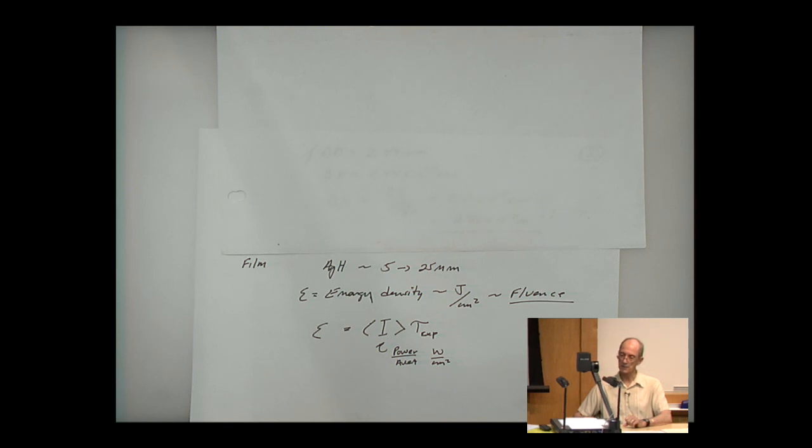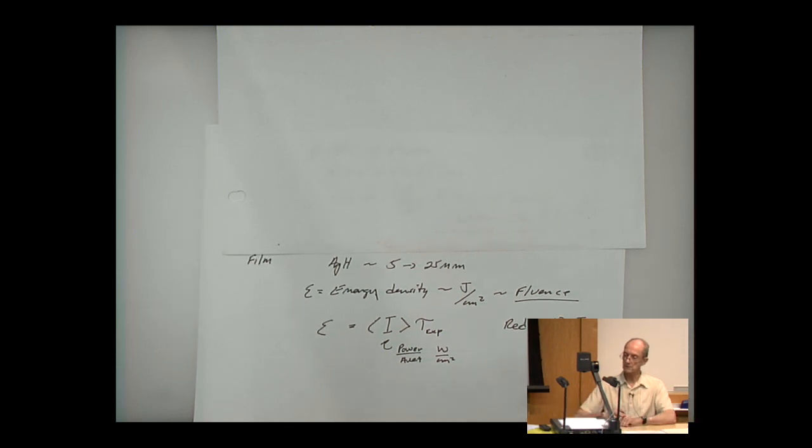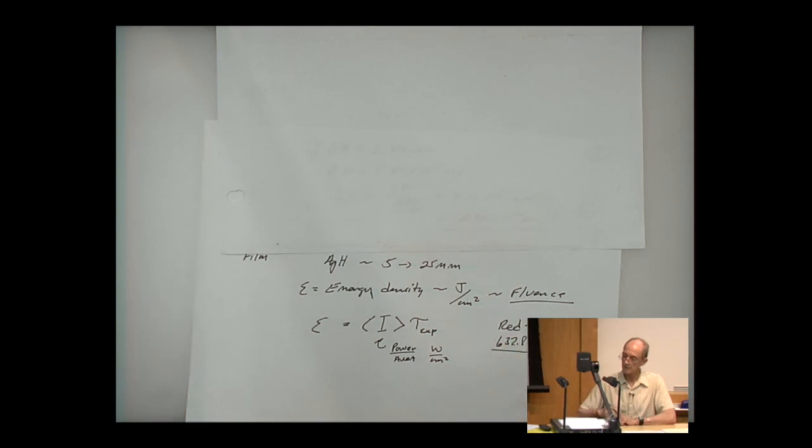And so in your case, for the polymer material that we'll be using, in the red, for instance, this optimum exposure density is around 18 millijoules per centimeter squared. Red being, say, a helium neon, 632.8 nanometer wavelength. Okay, so if we in general look at materials,